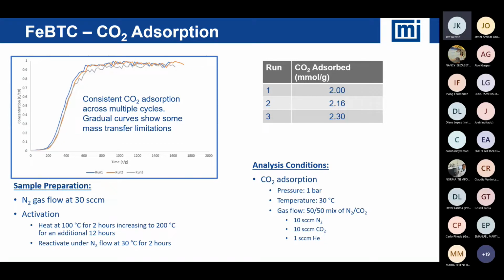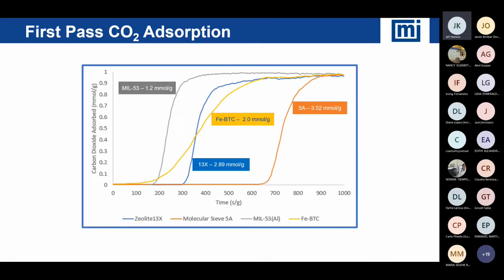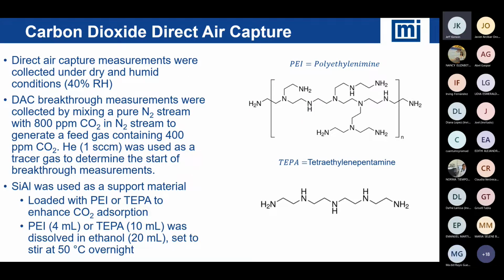And then likewise, we change metal organic framework, look at an iron BTC. Again, we see the same type of consistency as we did with the MIL-53, but a little bit more gradual, so we see some mass transfer limitations. The shape of the curve can be quite valuable. When we overlay all three of them, you see the performance there, that the 5A zeolite has some of the best initial performance. The 13X perhaps quite similar for robustness, and the MIL-53 quite a bit less capacity, but very robust and stable over the cycles.